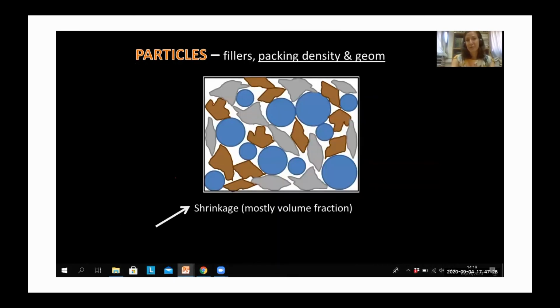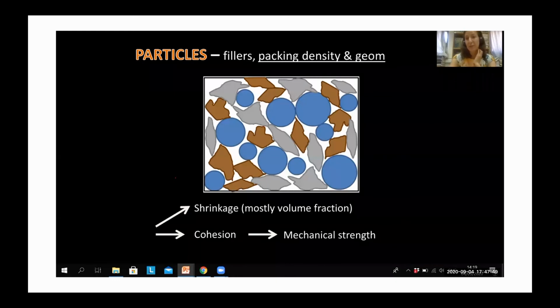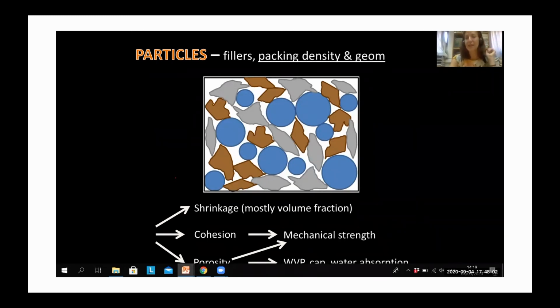So if we have an efficient packing density and geometry, we will have less shrinkage. So in terms of shrinkage, this will be beneficial, even if this is mostly affected by volume fraction, so by how many aggregates I have in my grout. Cohesion, which in turn has an influence on mechanical strength. Porosity, so this will have an influence on porosity, which in turn will have an influence on mechanical strength and other properties which are related, such as the passage of liquid water and water vapor. So basically it's on particles, and yeah, that's extremely important in grout design.